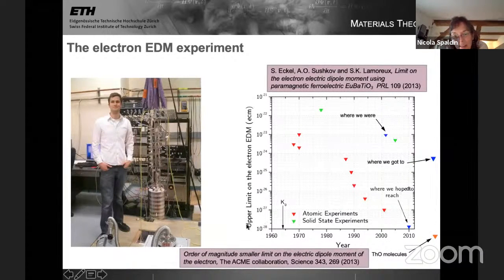So here's the plot then of the upper bound on the electron electric dipole moment as a function of time. And the red triangles are the atomic experiments on atoms or molecules, and the green ones are the solid state experiments. We'd hoped to get down to here, to about 10 to the minus 28 electron centimeters. Unfortunately, we only got to here. So we could claim that, well, we had the best solid state search for the electron electric dipole moment. But the material didn't perform as well as we'd hoped.